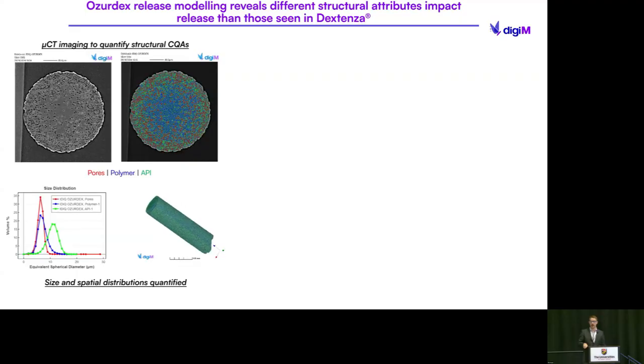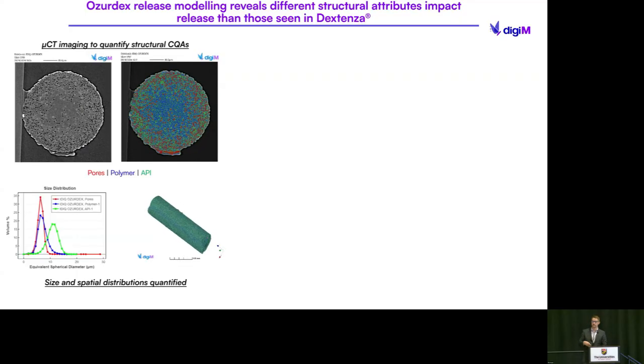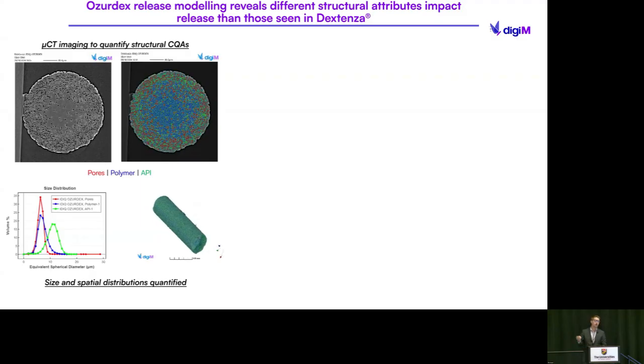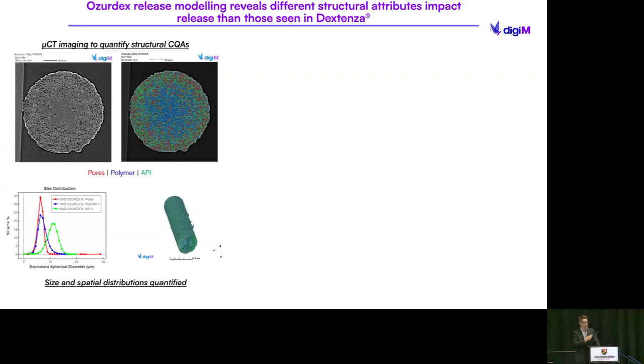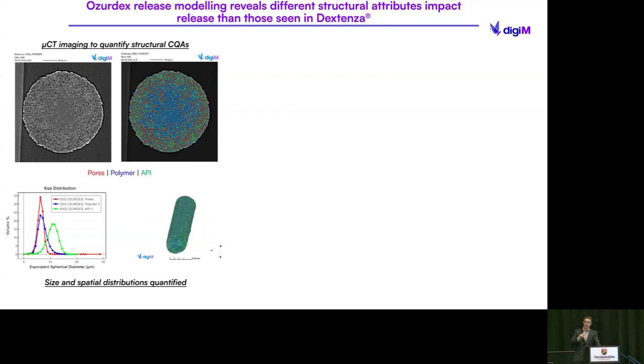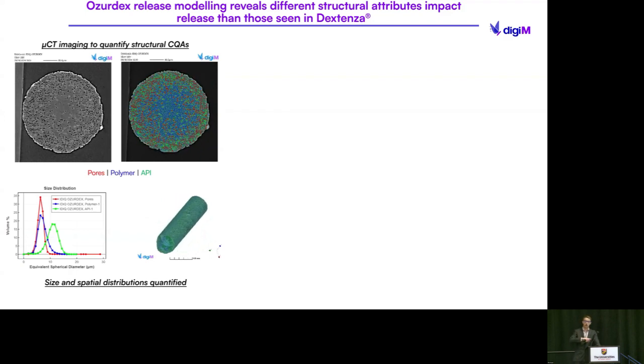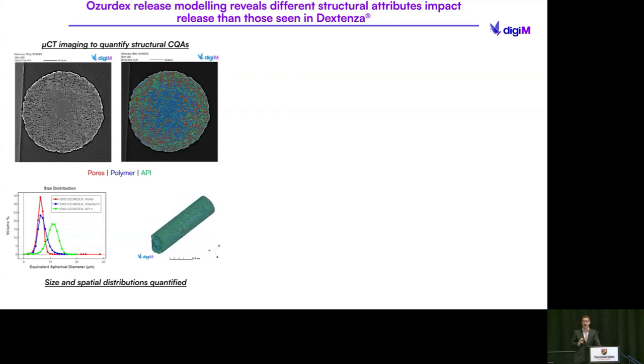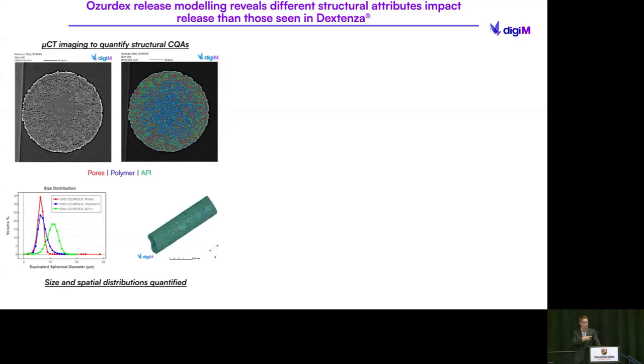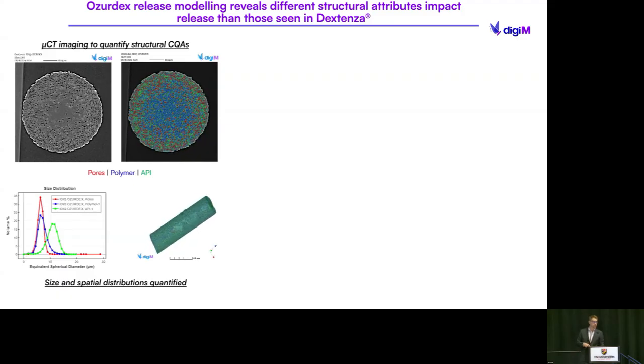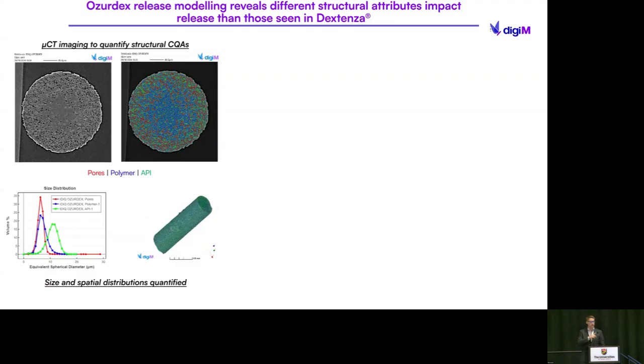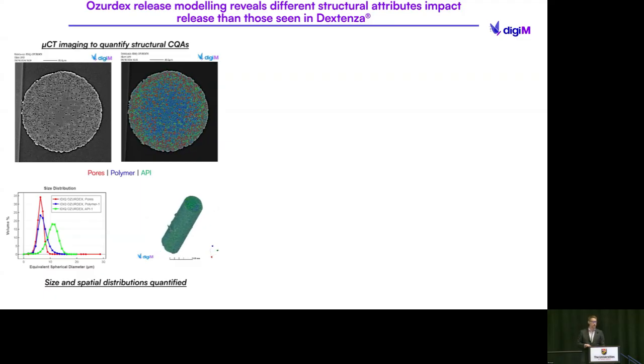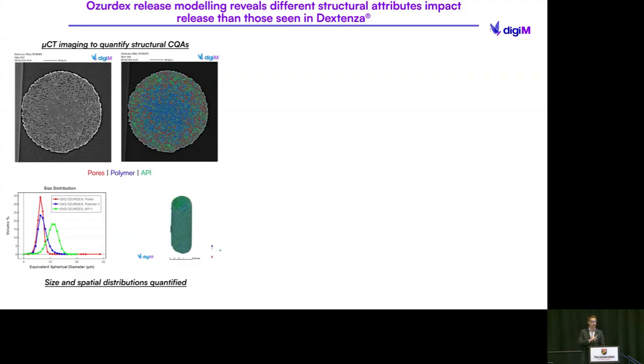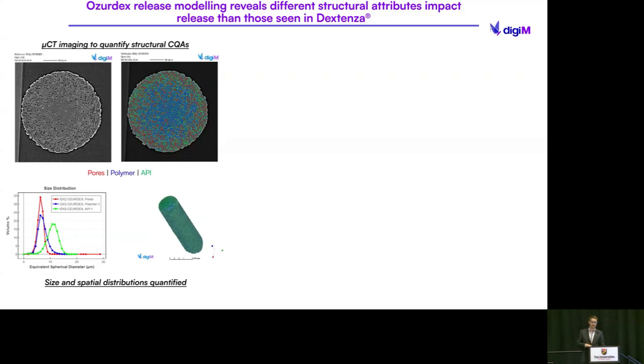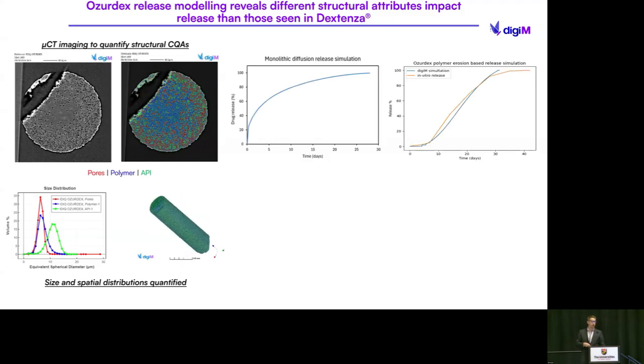But in regions that have a lot of API particles versus a lot of polymer domains, we can have variation in the contrast there. And so we're able to extract where the API likely are, where the most amount of API are, combined with the polymer and the pores. On the bottom there, we're showing the size distribution of all three of those domains, and then that model showing what the implant looks like. So from there, we progress down the same pathway we did with Dextenza. We go through release simulations.